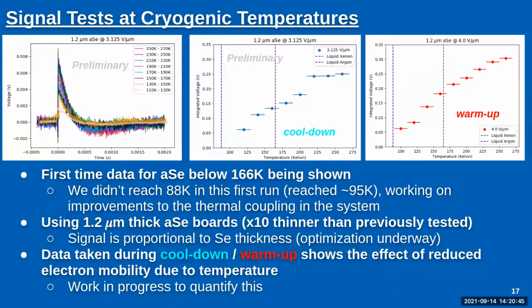So this is the punchline of what we got to see with data taken very recently. It's actually the first time, I think, amorphous selenium has been tested below 166 Kelvin, at least that I can find in the literature. We didn't quite reach all the way down to 88 Kelvin, the target for liquid argon, during our first run. We got down to about 95 K and then it just was not cooling any further. So we're working on improvements to better help the thermal coupling in the system.